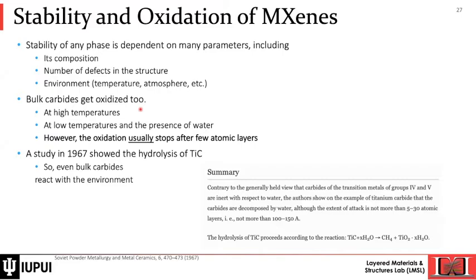But there are studies, maybe very few studies, that show that even TiC at room temperature in water can form oxides only up to a few atomic layers. So that's why the general knowledge about TiC and other carbides is that they are stable at room temperature, or in water. But the reason for that is when, for example, before the 2D materials era, we were looking at bulk, and no one really cared about 2 or 3 layers of atoms. So that's why they were called highly stable.